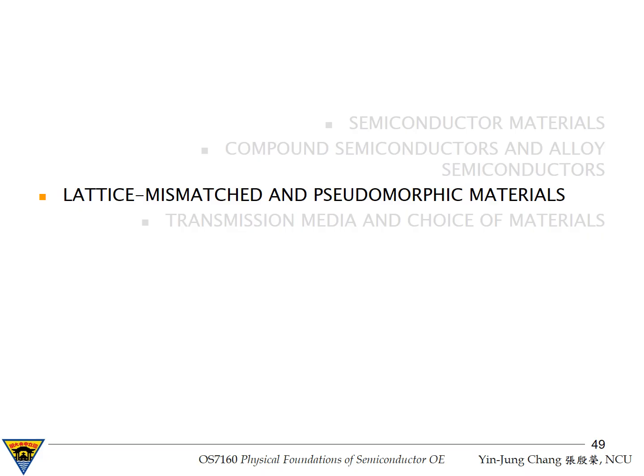What happens when we try to grow one crystalline material on top of another material whose lattice constant is not exactly the same? In real device fabrication, especially in optoelectronics, we almost never work with isolated bulk crystals. Instead, we grow thin crystalline layers on substrates using epitaxial techniques such as MBE or MOCVD. The moment we stack two different materials together, lattice compatibility becomes a central issue. It's very critical.